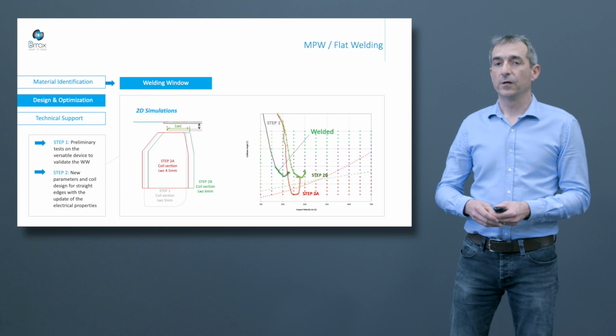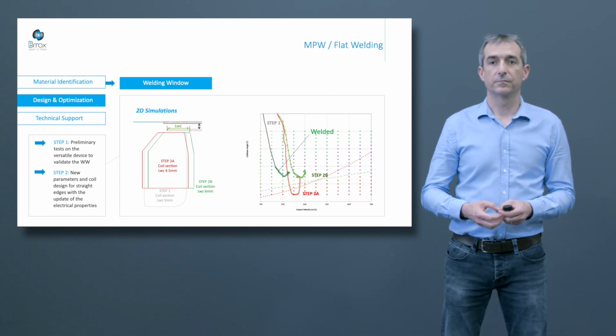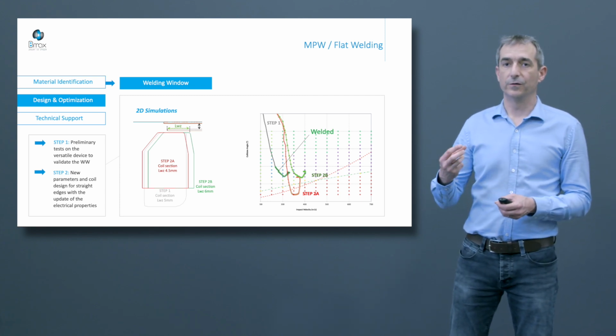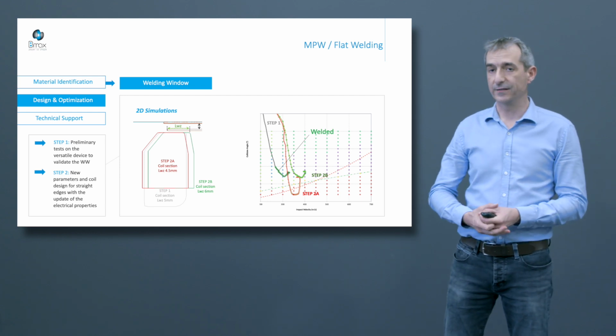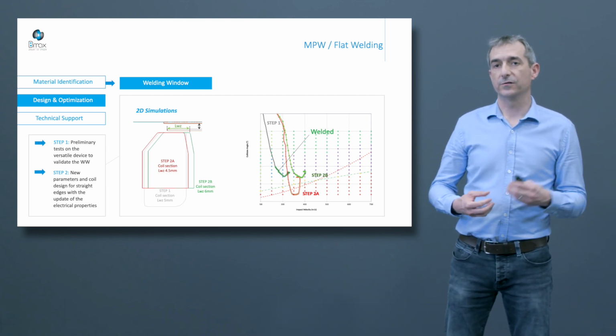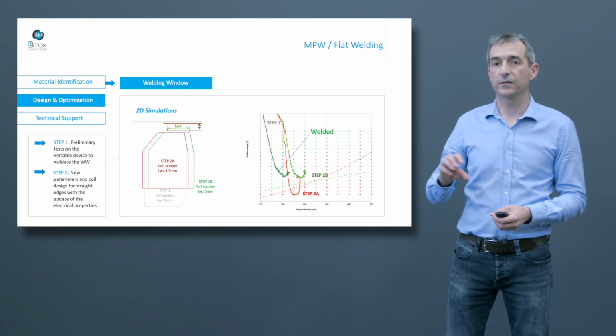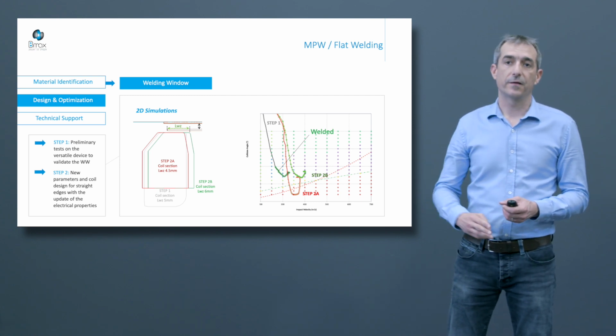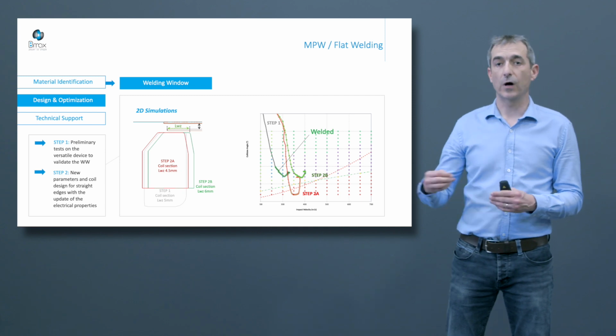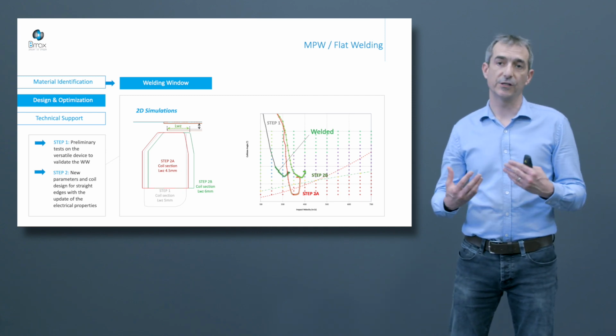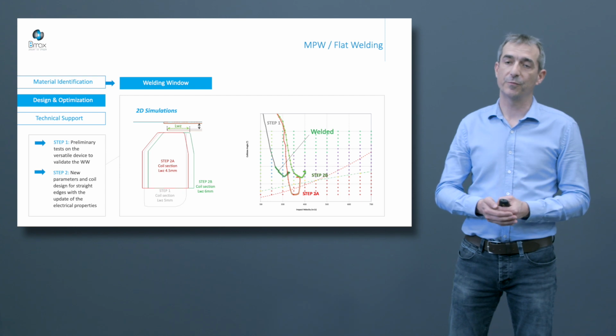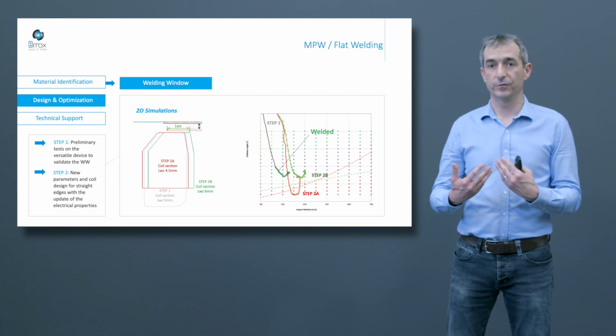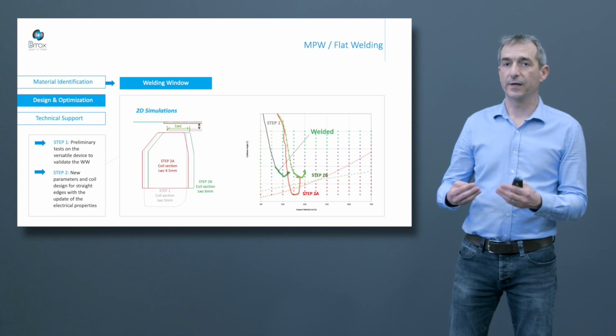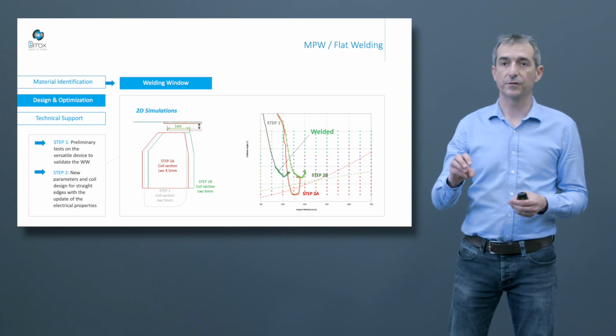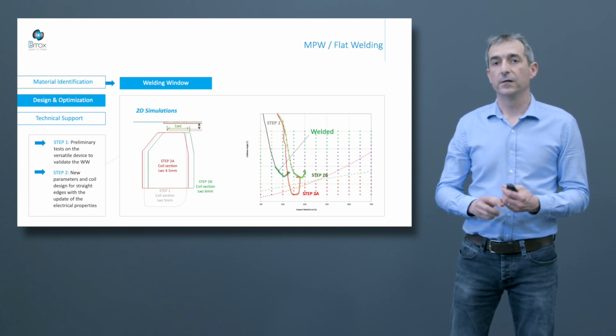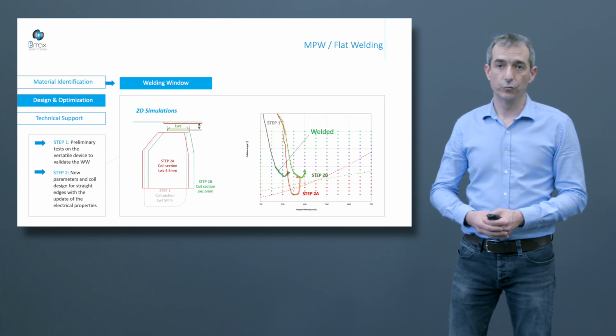After, in step two, we define a coil section, step 2A in red. But as in the previous example, we have a critical area. The path in terms of speed and angle goes out of the welding window. That's why we iterate: we change the coil section and the overlap between the workpieces, and by this way we optimize the process and the system with the coil section defined by the green area, named step 2B.